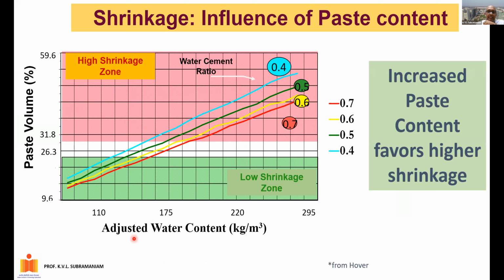So if I start looking at paste contents, it's not just the water to cement ratio. As I start increasing the paste volume in the concrete, I get into the high shrinkage zone. And these are concrete mixes that have a high tendency to crack.